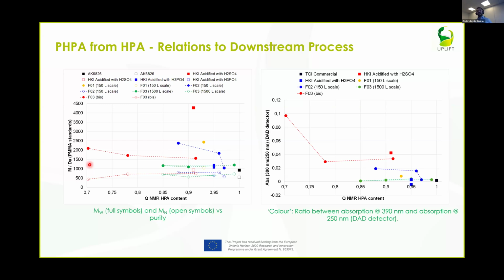So we actually are able to use a low purity monomer to produce a polymer in the end. This is highly interesting because, of course, whenever you do additional purification steps, you also reduce the overall yield of the compound. And therefore, it's very interesting if we can use a less pure stream to actually produce new polymers. Of course, if these impurities result in a discoloration of the product, then it becomes less relevant.